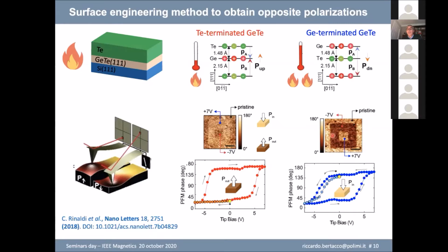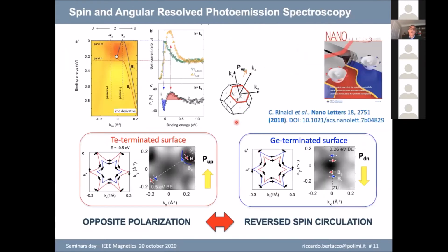And you see that, especially here, it's clear that the pristine states correspond to a polarization inwards, but we are able to write now the opposite state of polarization corresponding to this picture frame. So the idea was, okay, we are able to prepare a sample in a pristine state which has a polarization pointing, as in this case, downwards, or as in this case, outwards. And we can also write domains, which means that it's really ferroelectric, which can be written. And in these experiments, which are spin-polarized angle-resolved photoemission experiments, we really checked that we reverse now the sense of circulation of the spin when we change the polarization. And this is done looking at the bands here without entering the details. It's just, I'll say, a sort of prerequisite for the talk today.